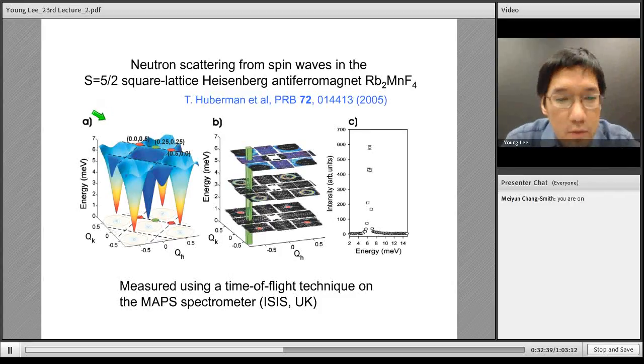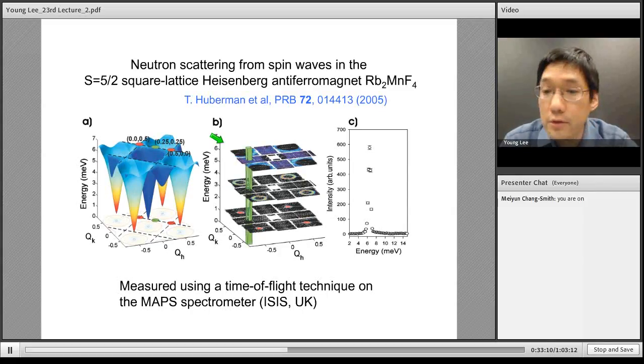Some of the results are shown in these three panels. I guess this is the artist's rendition of what their data looks like, and there's a color code for the intensity. Here are some of the actual data. Cutting at different energies through these cones, you can see that you have these rings at some finite energy. The rings are almost like dots at very low energy down here, and at very high energy, you're looking at the zone boundary magnons.